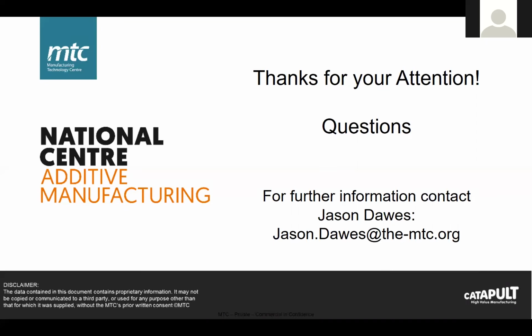Okay. And then we had some questions come in prior to the webinar taking place today. Again, one for you, Jason: how do we know when a powder reaches the end of its usable life? It's a good question. Generally speaking, we want to have a specification for our material up front. The reason I usually see for a powder coming out of spec is something like interstitial oxygen going above that level. Like we discussed on the recycling case study, when we use a titanium material, oxygen content does increase over time, probably more due to events such as spatter and heat affected zone rather than general pickup from ambient conditions. But once that oxygen gets too high, that's certainly time to put the powder away and stop using it.